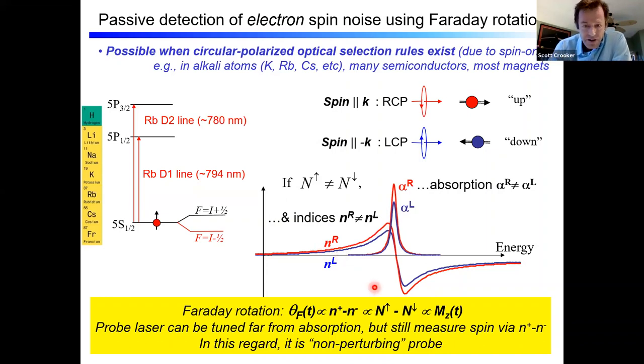But this is great news for Faraday rotation and methods like this, because that means we can tune the laser way out here, far away from any absorption, but still be sensitive to the magnetization via its influence on the indices of refraction. I should have pointed out that, as you remember, absorption tends to decay as 1 over detuning squared, but the dispersive part, the index, decays much more gently as 1 over detuning.